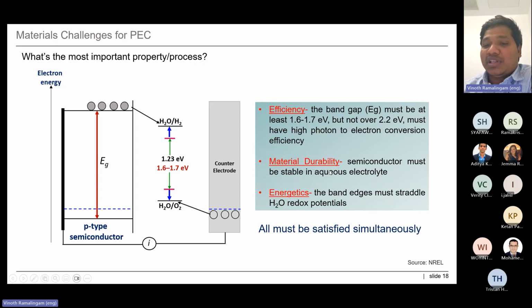And the second one is the durability, because the water splitting reaction is a harsh reaction. The photoelectrodes tend to degrade so quickly that they lose their performance. In that case, the semiconductor must be stable in aqueous electrolyte. And the third should be the band edges. As I mentioned earlier, the conduction band should be more negative than the water reduction potential, and the valence band should be more positive than the water oxidation potential. Then you will have a better water splitting reaction. So all of these must be satisfied simultaneously in order to achieve better PEC performance.